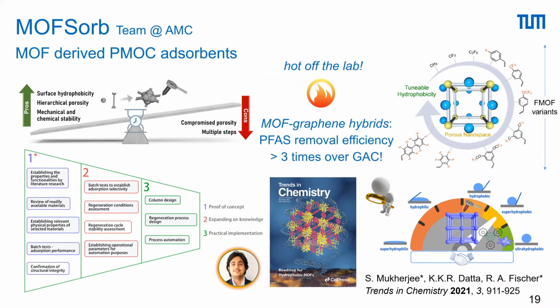So this is the roadmap of steps which you have to take into account. So we do a proof of concept, then this needs to be expanded, and there must be practical implementations, and we are just at the first column. And what is done, we investigate, of course, metal organic frameworks, play with the surface hydrophobicity, with the hierarchical porosity, and of course it must be mechanically and chemically stable. But there are, of course, problems with multiple step synthesis and compromised porosity if you integrate various components in a working hybrid material.